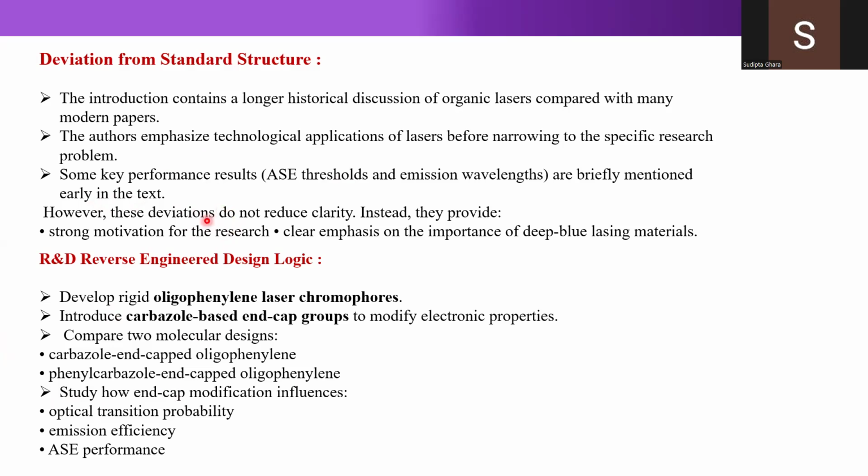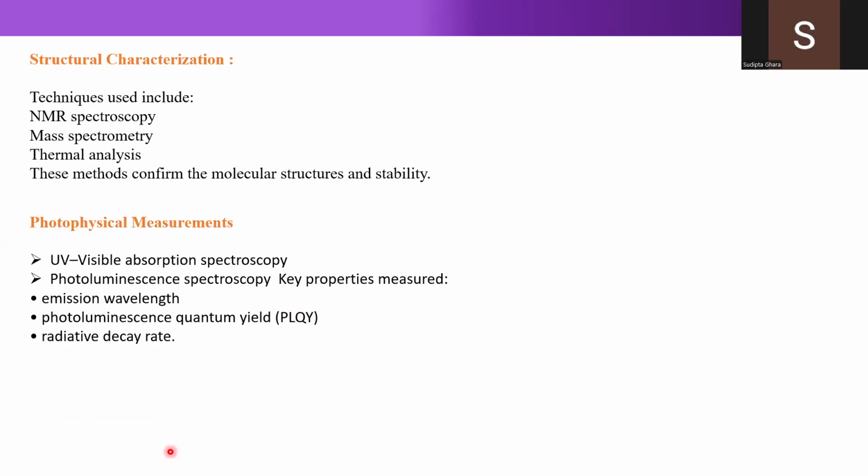And now the reverse engineering of the paper. So now we analyze the research and development strategy. The author designed a rigid oligophenylene laser chromophore. They attached carbazole and phenyl carbazole end groups. The reason behind designing these carbazole groups is their strong electron-donating ability, which influences the optical transition probability, emission efficiency, and ASE measurement.